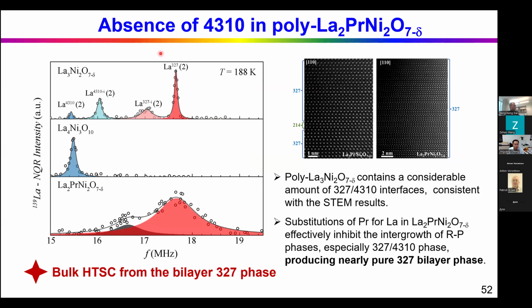In comparison to this undoped sample, we also measured the NQR of the trilayer single crystal. Indeed, for this peak on the left side, they have the same frequency. So this confirms that indeed in the 327 phase, there's some trilayer phase. But for the praseodymium doped sample, we only observe a very broad peak for this 327 phase, and there's a side peak around this side. But definitely there's no trilayer phase, and also no intergrowth with this phase. So from this result, we can basically confirm the bulk high TC superconductivity indeed comes from the bilayer 327 phase.